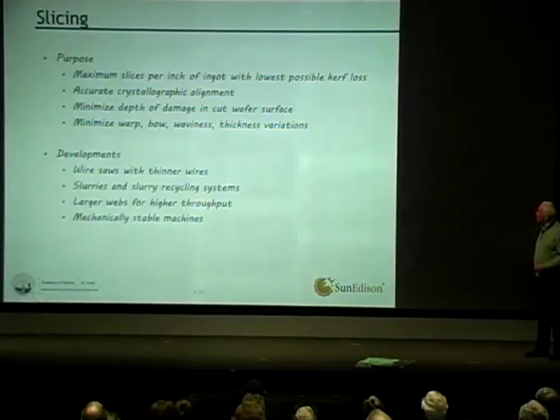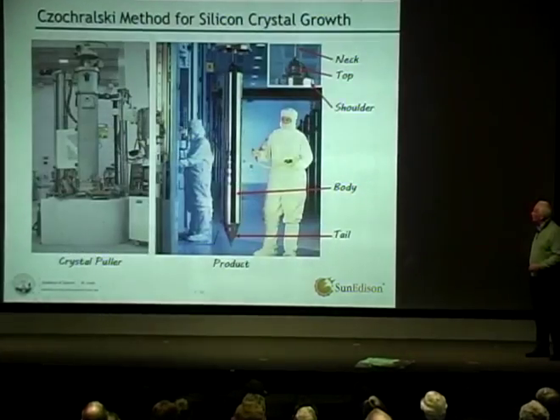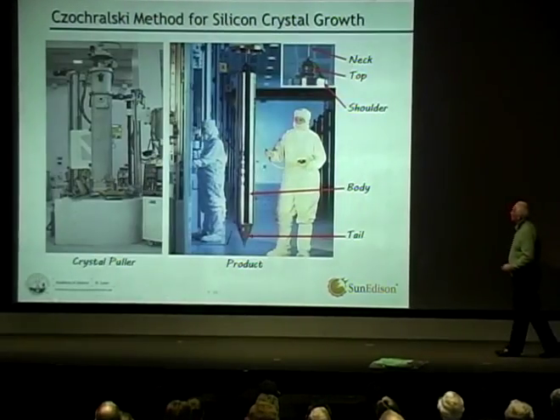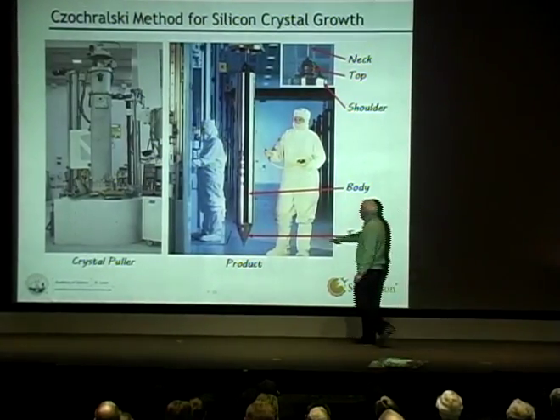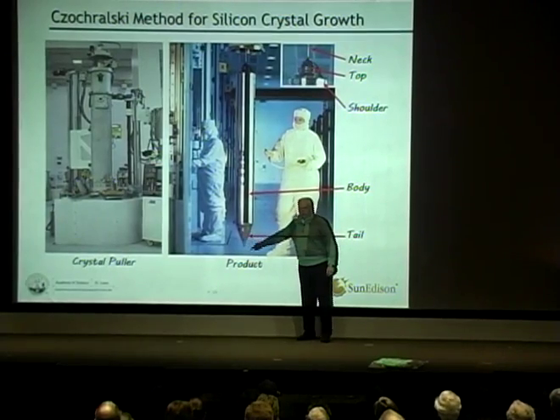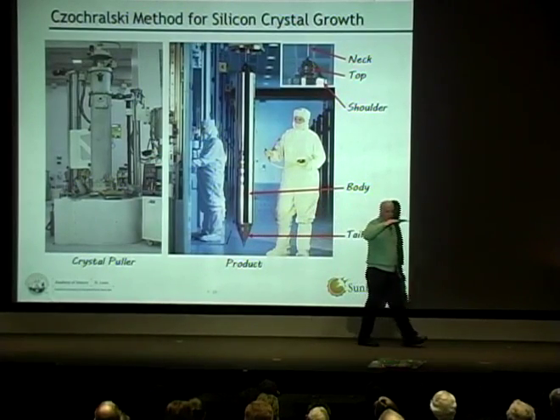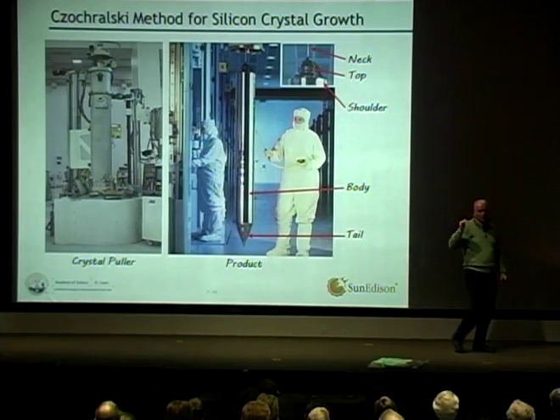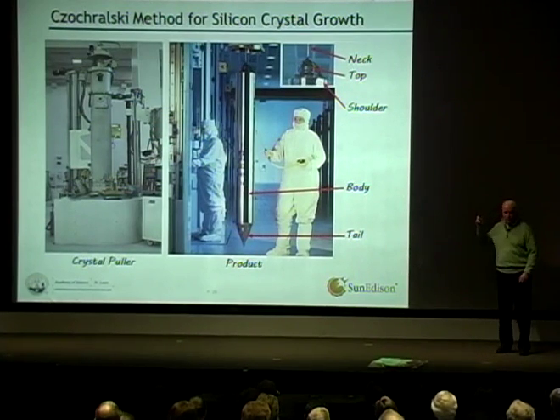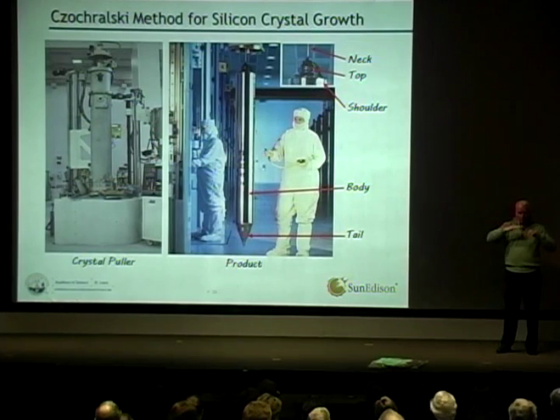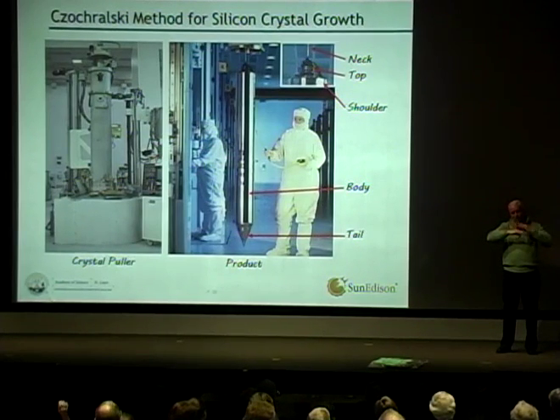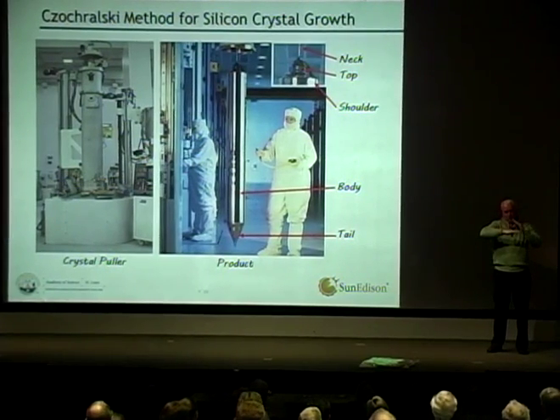What happens is, when you pull the crystal out, if you just did that, you would indeed get thermal shock. That's why we have this tail. And you see it's like a cone. The reason is, if you just have thermal shock, you would create dislocations exactly the same way as you would when you put the seed in. But in silicon, remember it's cubic, and when you create these defects, the dislocations go on a glide plane at 45 degrees to the melt interface, like that.